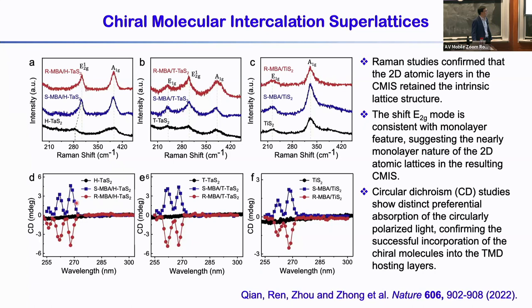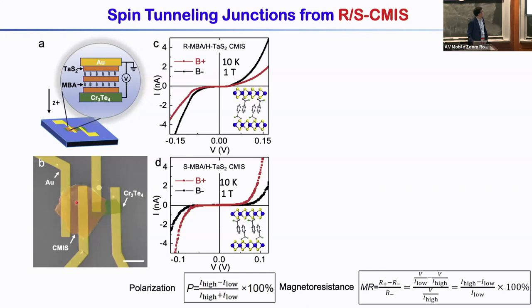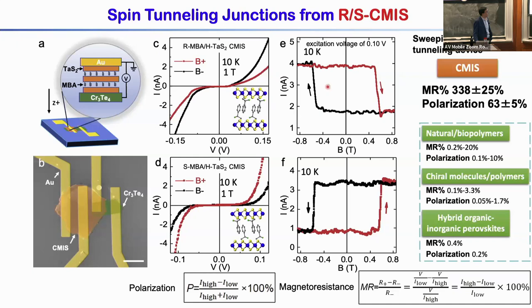Next, we try to look at the spin selectivity. We created a spin tunneling device — basically we use a ferromagnet to polarize the spin of injected electrons and see how spin-polarized electrons transport across this structure. We quickly find that with spin-polarized electrons, depending on the chirality, they have very different transport properties. In one chirality, they have a higher current under one magnetic field direction, and in the other chirality, they have totally opposite behavior. The magnetic loop study shows a clear spin selectivity, and we could further quantify the spin polarization ratio or magnetoresistance ratio that actually exceeds state-of-art devices made from these types of chiral molecules.